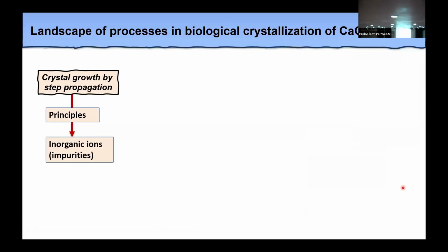So again, the AFM was this huge step forward for understanding crystal growth in aqueous solutions. People had thought about crystal growth at ultra high vacuum, but being able to image growth in the presence of water was just an extraordinary change for the community. And here's a picture of my friend Jim. What they were doing at Lawrence Livermore at the time were growing these massive, and I mean massive, single crystals of KDP for laser applications. And they were trying to understand all the factors that would affect impurity contents. They deployed this new AFM method to look at some of those things, and they had imported some folks from Alex Chernov in particular to help them with the crystal growth theory. And we took those same technologies and theories and applied them to step propagation, or crystal growth, in calcium carbonate.